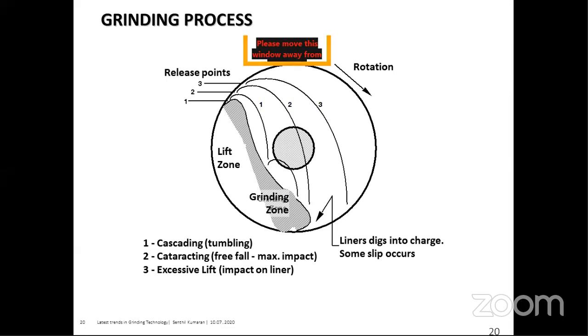So when the gravitational force equals the centrifugal force, in this rotating equipment, where we fill the media up to 30% in the mill, if we rotate at the critical speed, all the balls will stick to the walls of the ball mill and will not fall down. Then the impact or the attrition will not happen, so effective grinding will not happen.